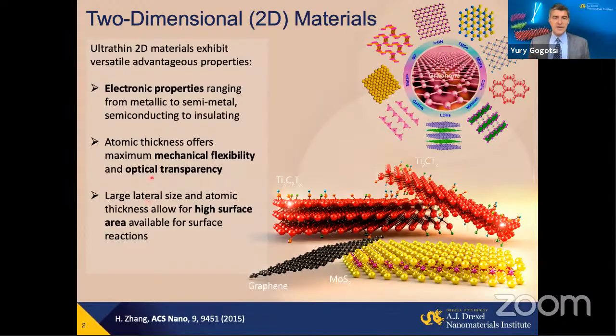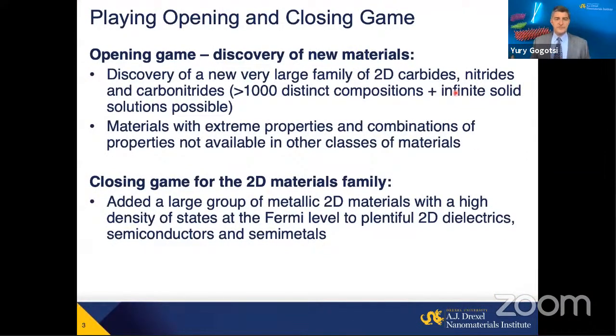So MXenes actually played an interesting role here. They are the most metallic of the available freestanding two-dimensional materials. So when we discovered them, we not only played the opening game for a very large family of materials, and I will convince you later that we can have at least 1,000 well-defined chemically defined structures plus an infinite number of solid solutions with very interesting properties.